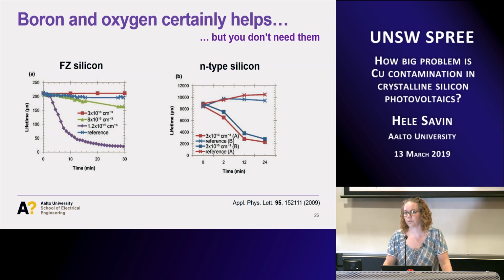It's quite interesting because the trend is very different in these two samples. You mean which trends? With and without. So these are non-contaminated. This is supposed to be similar, and these two are. Do I have a mistake here? No, these are the contaminated ones. So what are you saying is different? The idea is to show that they are similar, and they are similar. And if you have copper, you see degradation. So this is just to show that we don't need boron to have copper LID. That was the point of this experiment. Just check that publication, it's the same type of wafer, just sister wafers. Okay, all right, thank you.